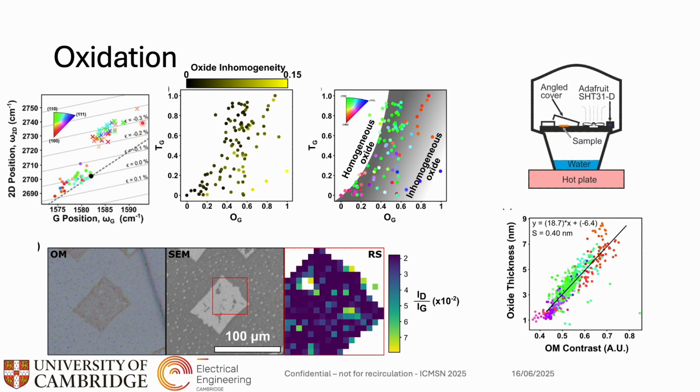And you can see a very clear trend here. The graphene prior to oxidation is quite strained to varying degrees, but after oxidation it relaxes to a strain of around 0 if these empirical Raman measurements are accurate. And there's a little bit of debate on that, but in general you can see the trend of a relaxing strain. And this is representative of effectively the graphene decoupling from the copper substrate.